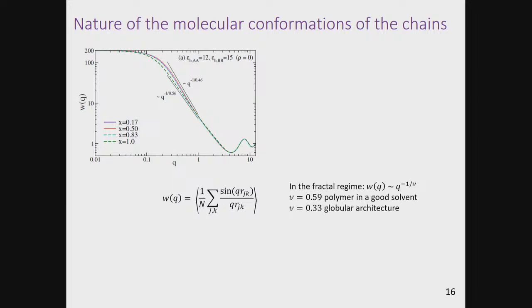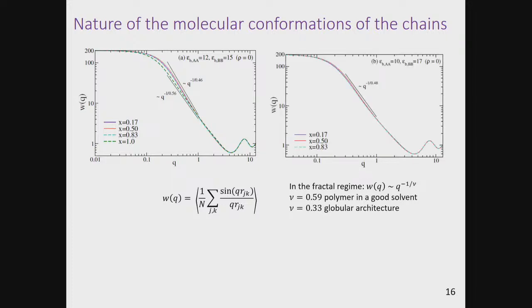So as compared to the pure case, which is x equal to 1, the form factor exponent here is 0.6. But when you are in the dual cross-linking limit, you see it to be 0.46. So clearly, we can form more compact structures with dual cross-linking. And we don't see much difference when we change this bond energy disparity.